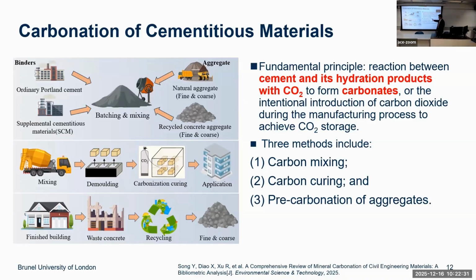So there are three ways: either carbon mixing, where the carbon dioxide is injected while mixing, or carbon curing. That's one of the main things we're doing, carbon curing. And also you could pre-carbonate the aggregate, mainly recycled aggregate, then mix with the other components for making concrete without any difference from the current technology. So these are three ways to do that.